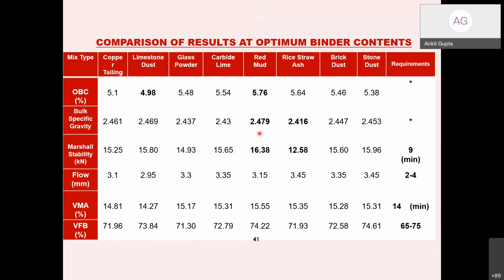And if you see the properties which are required as per the guidelines, most of these fillers are passing those properties. Like if you see the bulk specific gravity, again, the bulk specific gravity is in a good range of 2.45 or 2.47. So it's a good bulk specific gravity we are getting. The Marshall stability should be 9 minimum. We are getting obviously values more than 9.